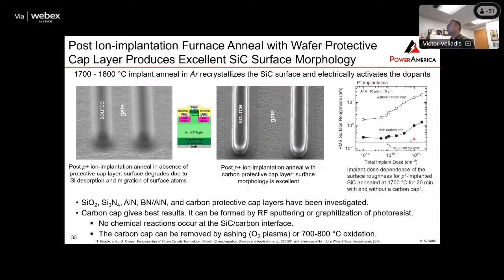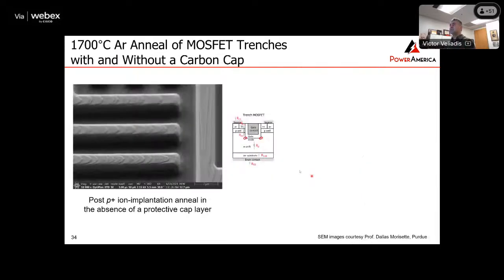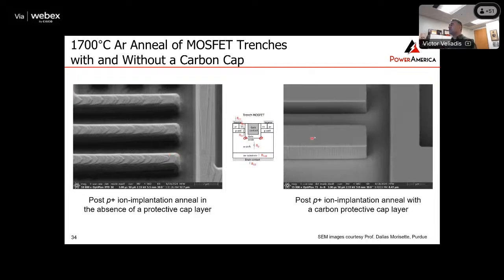And you can see here the roughness with the carbon cap. Even at high doses, the roughness is relatively low. But then if you don't use a cap layer, then you get a very rough surface. So the bottom line is, when you do the implantation anneal in silicon carbide, you need a cap layer on your wafer. And this is another example where you see that there is no cap layer, and you can see what the surface looks like. It's relatively poor. And then here's the situation where you use a cap layer. So basically, the high temperature anneal in silicon carbide requires a cap layer, and carbon is the best to use.